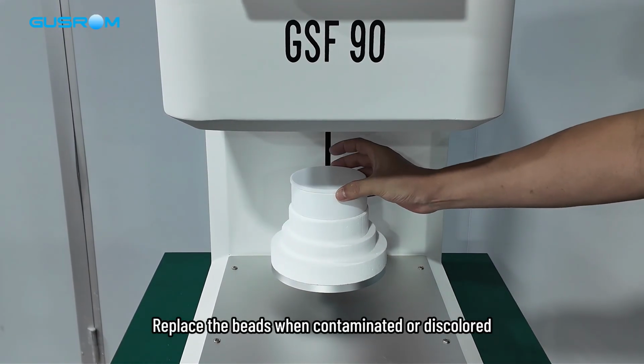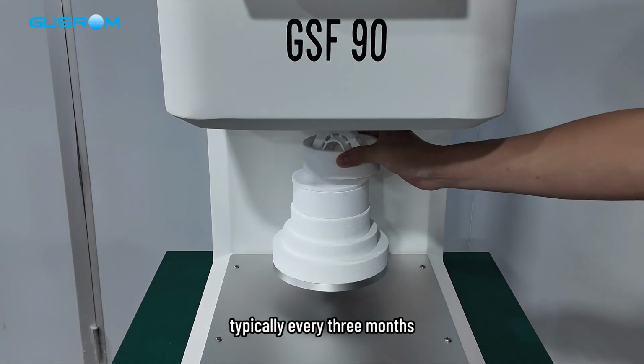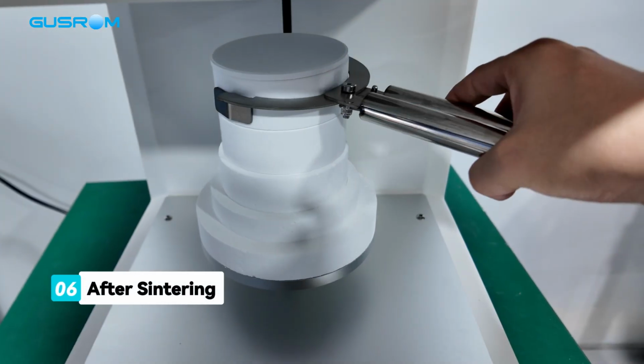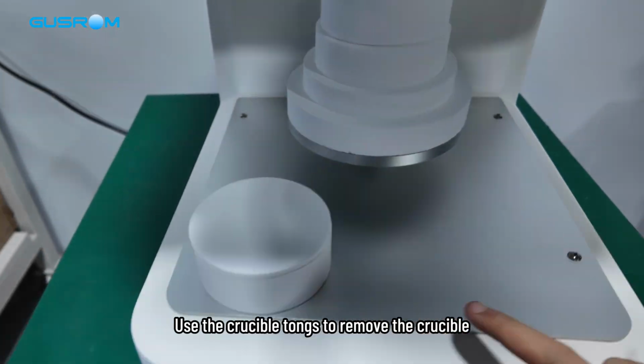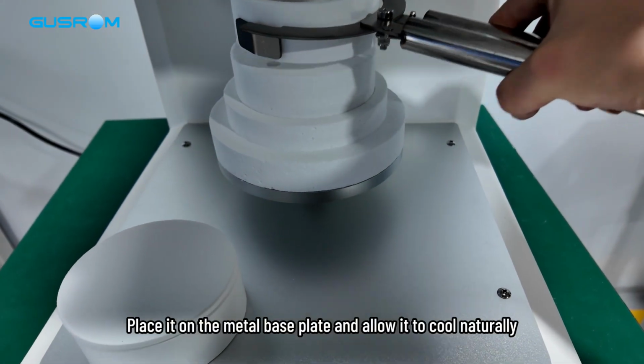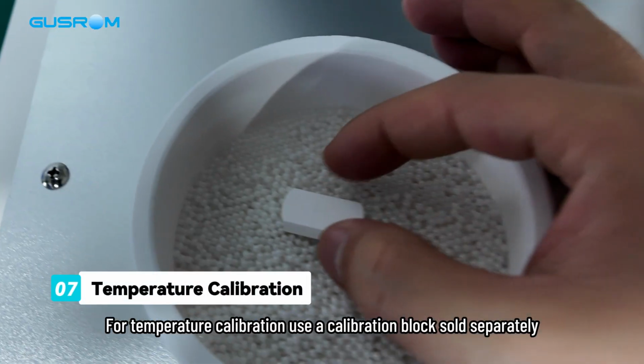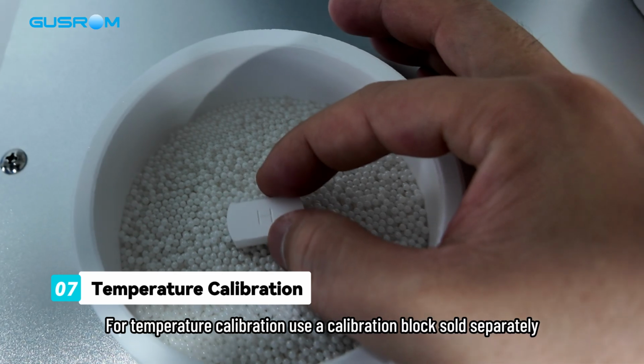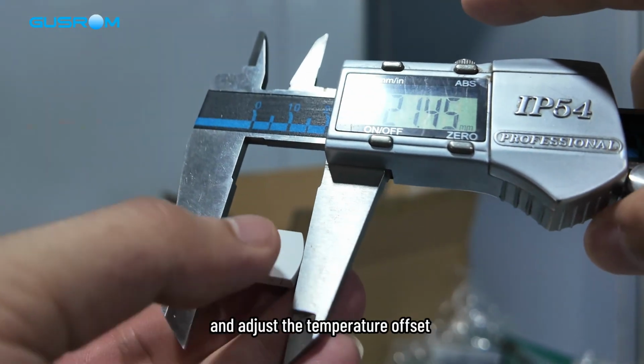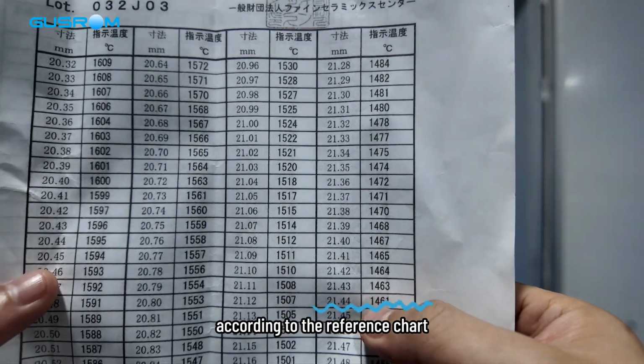Replace the beads when contaminated or discolored, typically every 3 months. After sintering, use the crucible tongs to remove the crucible. Place it on the metal base plate and allow it to cool naturally. For temperature calibration, use a calibration block, sold separately. After standard sintering, measure the block size and adjust the temperature offset according to the reference chart.